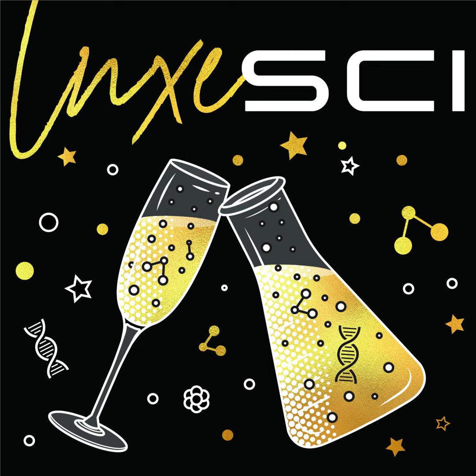And so X-ray fluorescence is one of those ways. What's great about X-ray fluorescence is you can scan an image left and right, just raster scanning the image, let's say with a robotic device that sits in front of the painting, and get a map of every element and then map the elements and redraw the image in a different spectrum. And all of a sudden now you're wearing these reflective glasses that can see different spectra. It's pretty exciting. It's very cool. That technique is also completely non-destructive, which is very important. I think that's really the crux of the whole thing, right? You can get so much important information about an artwork without having to take it apart. Yes. So that's the other way.